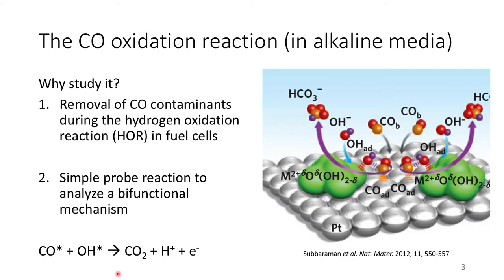What I mean by this being a bifunctional reaction is what's demonstrated in this image from the Markovic group at Argonne. In a system where there is submonolayer deposition of a metal hydroxyoxide film on a platinum surface, CO will adsorb at the platinum sites. OH is generated at the hydroxyoxide film, likely by enabling water dissociation. The CO and OH can combine to generate carbonate and subsequently form CO2.